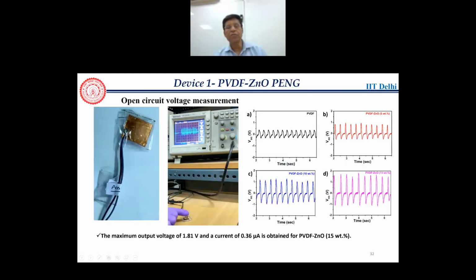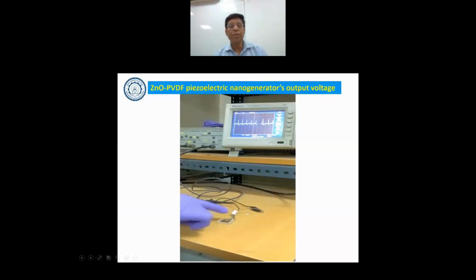And in this characterization, we did the piezo amplitude versus DC bias measurement, and from here we calculated the D33 parameter. And if you see here, the D33 parameter goes from 55 picometer per volt to 70 picometer per volt. So the D33 parameter gets enhanced, which shows that these nanocomposite films basically have a higher piezo property. Okay, so there are more details of KPFM measurements, how we did all these things. Maybe due to shortage of time, I will just skip to this.